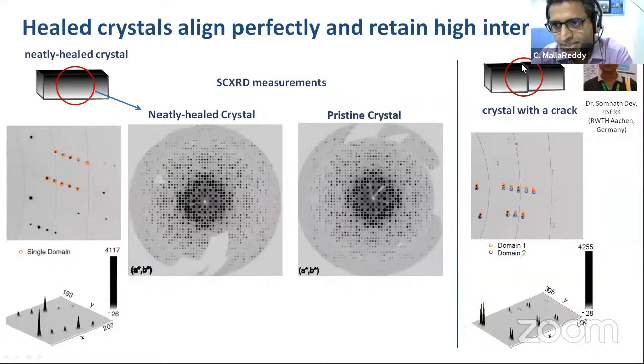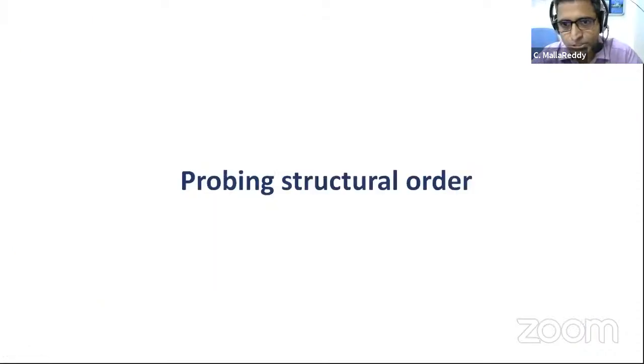But if the healing is not good, so the domains are not nicely aligned, that is why you see split peaks. So this domain and this domain are not fully aligned. There is a mismatch. That's what we could see from that.